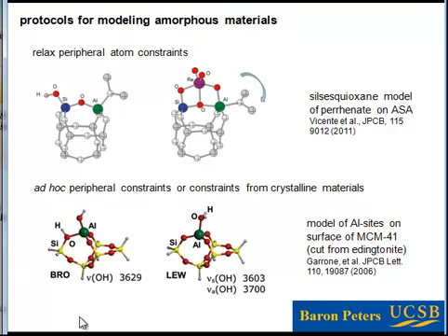And one of the typical ways of doing this is to carve a small cluster model out of a zeolite or out of quartz or cristobalite or something of that sort. And this is a common way of modeling localized amorphous regions on silica or silica alumina materials. The problem, of course, is that you don't have a whole large distribution of sites to choose from, and the sites that you're modeling are actually representative of the quartz or the zeolite that you started from. They're not really necessarily representative of those most active sites that might actually even be dominant in the reaction chemistry.